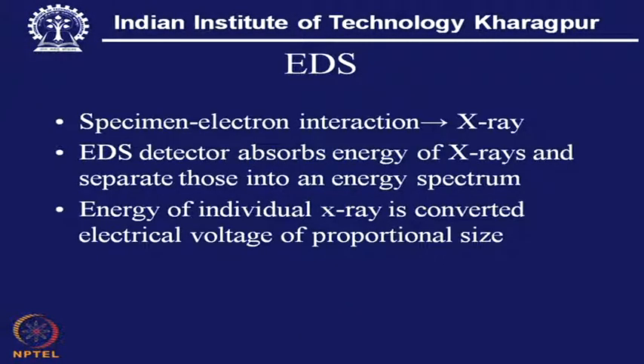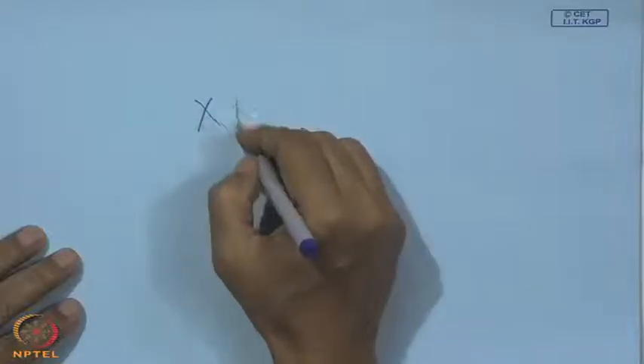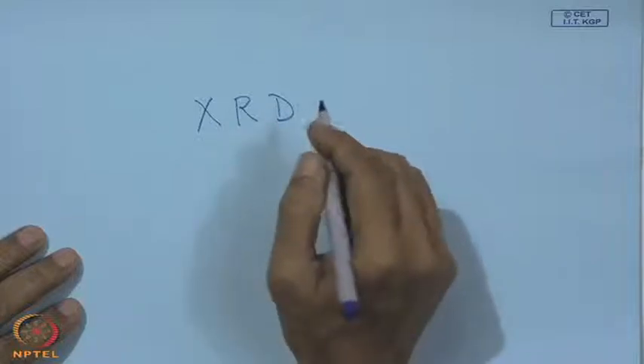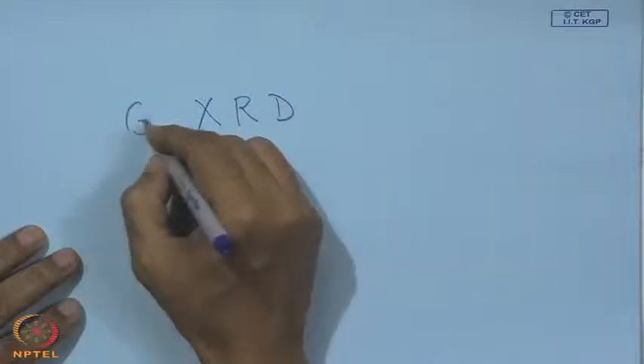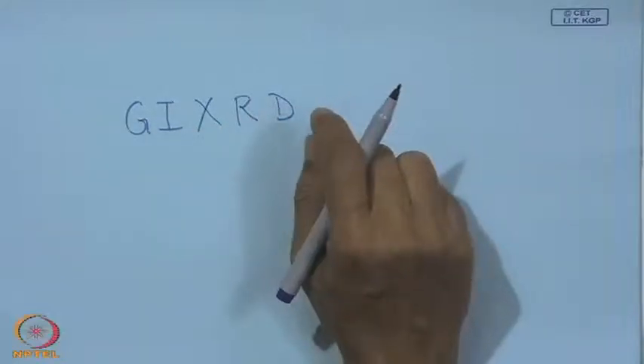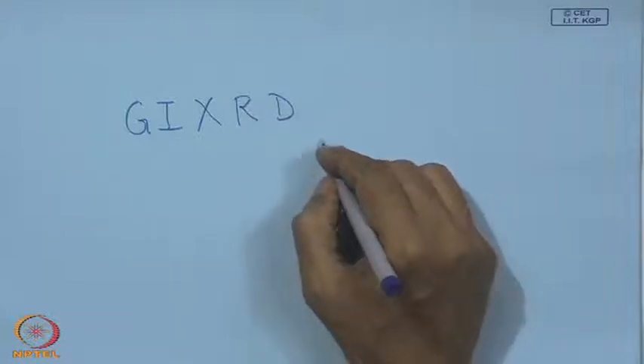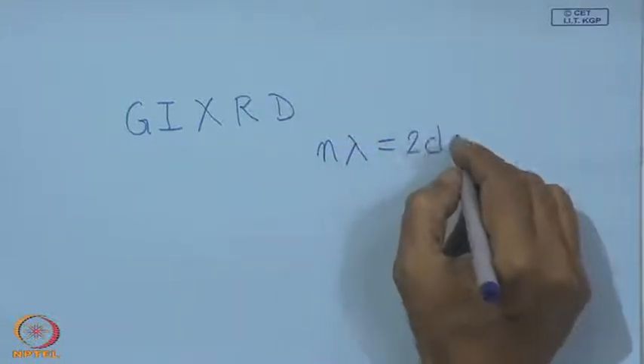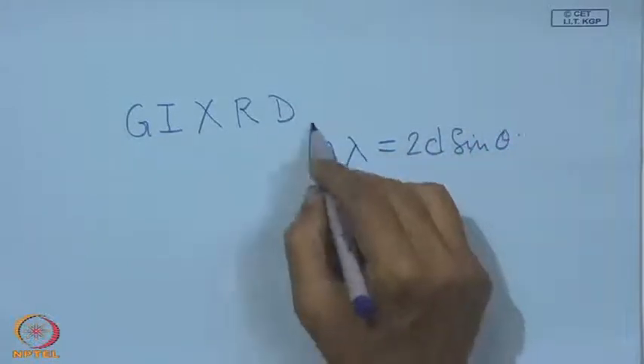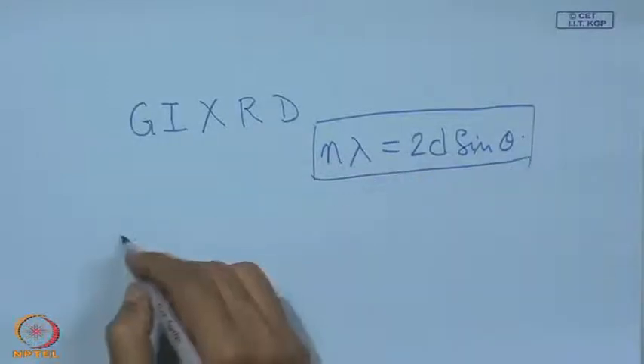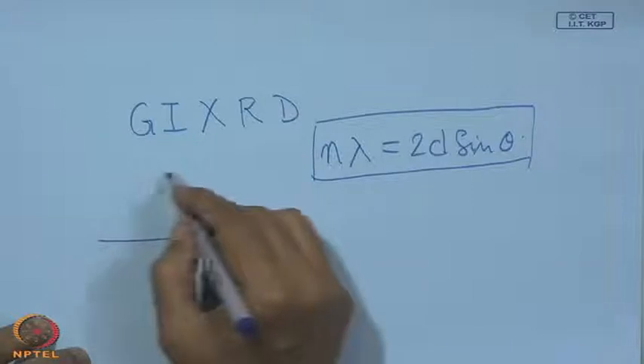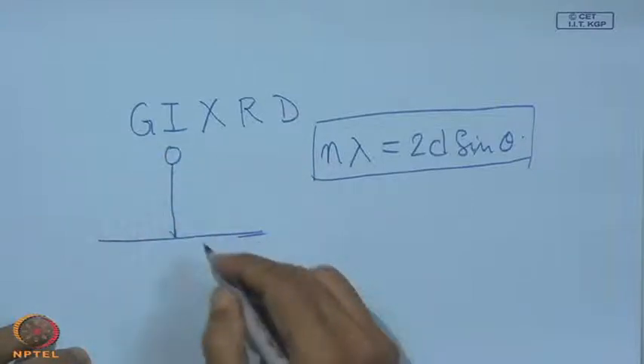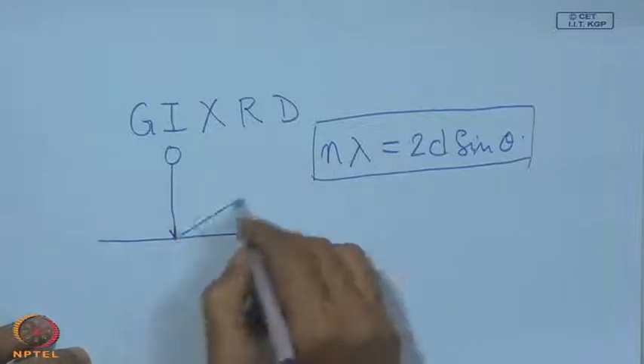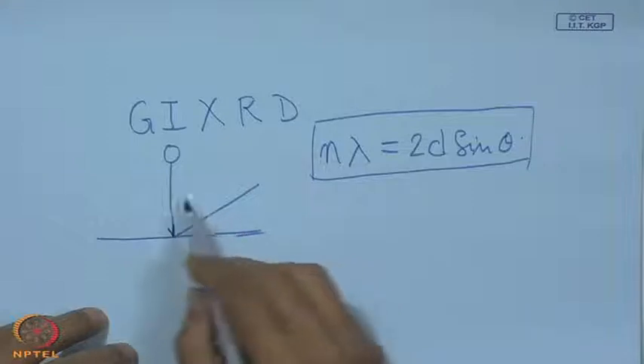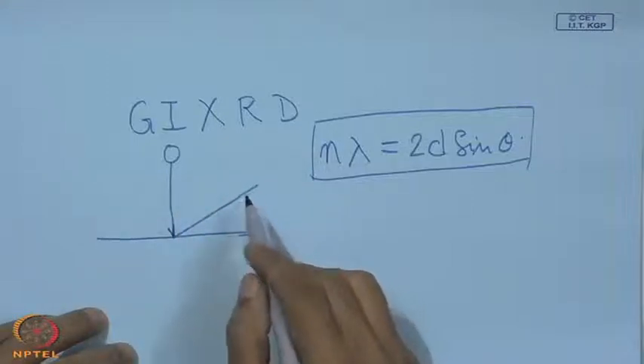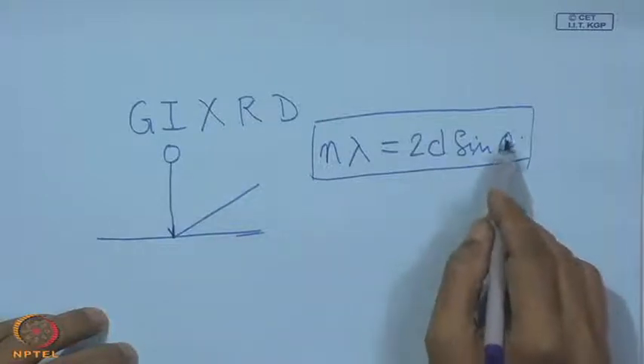Now, we can also have, say, XRD. Now, XRD means X-ray diffraction diagram, and it can also be GIXRD, that means it is for the film. Now, what we see in this case, we also know that this is n lambda = 2 d sin theta, that is the Bragg's law. So, depending upon the X-ray which falls on this surface, from the X-ray source it is falling and there will be a diffraction. So, there will be a diffraction and the detector is going to capture this diffracted ray depending upon the value of theta.